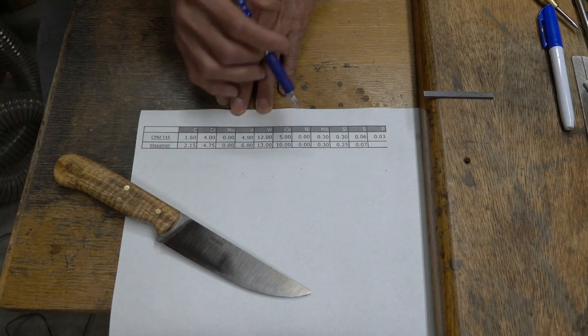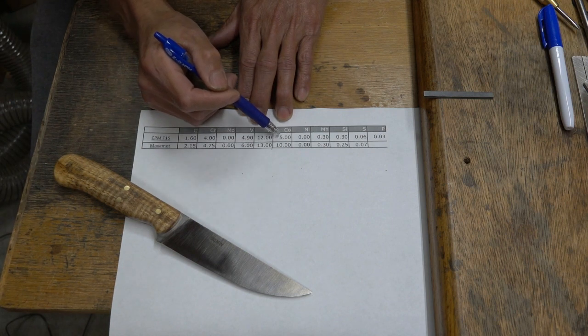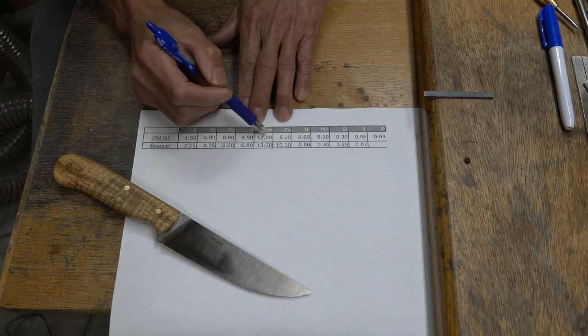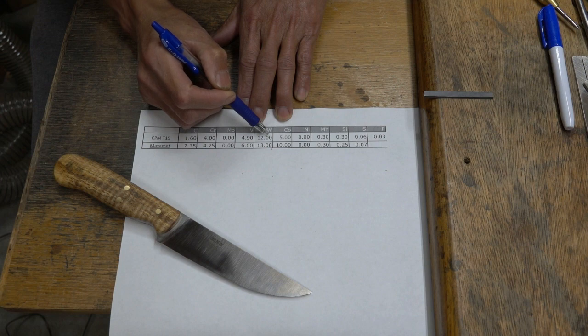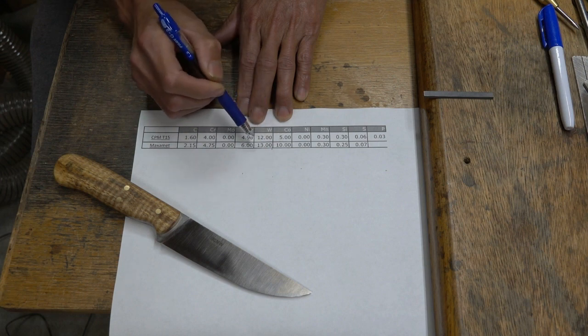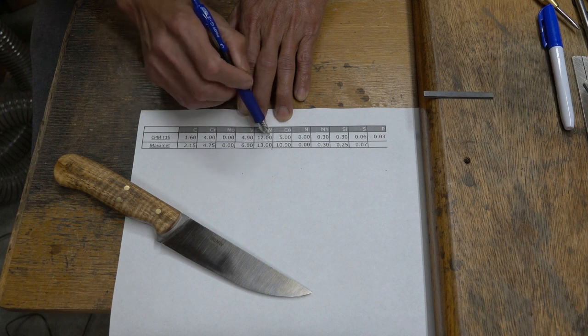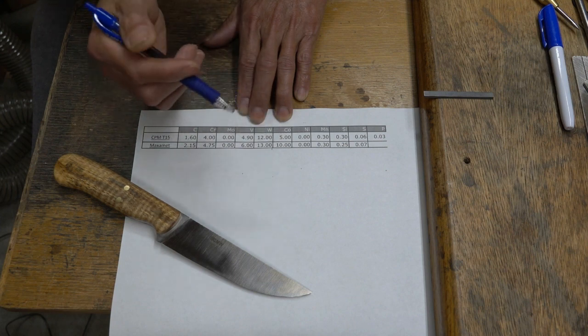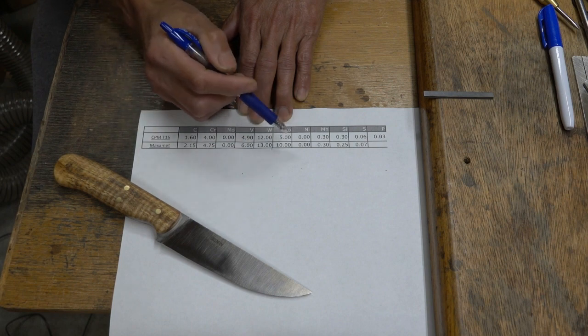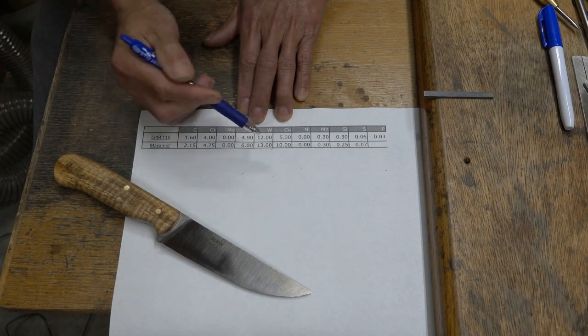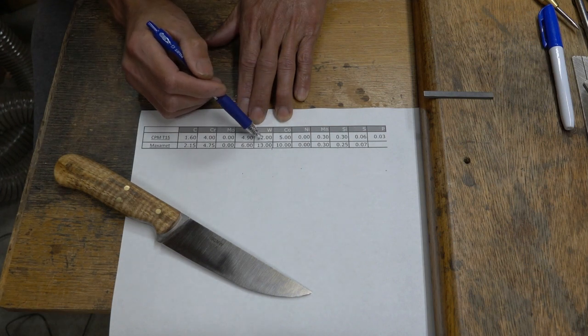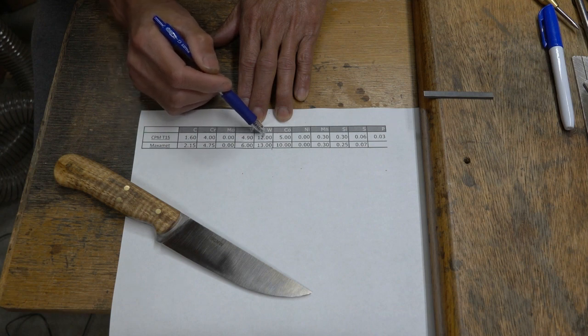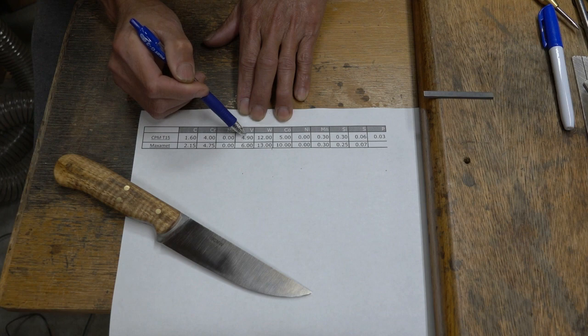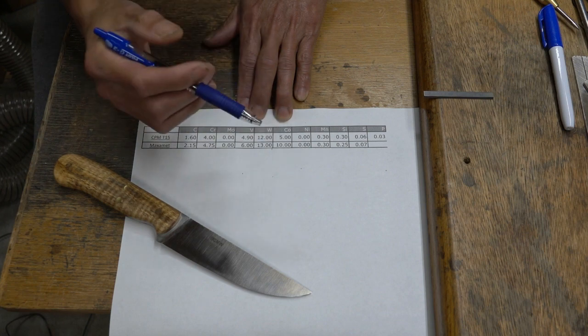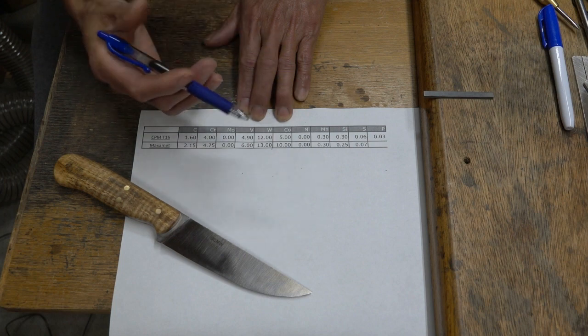And so the cobalt, that matrix we were talking about before, cobalt is very efficient to distribute itself around and also around the interface of all these carbides. Now the 5% is, say, okay, let's put it right next to all these particles, tungsten and vanadium carbide. And again, this time mental calculation projection, 5% will provide most of the interface needed to hold on to tungsten carbide and some vanadium. The rest is going to be the cobalt matrix.